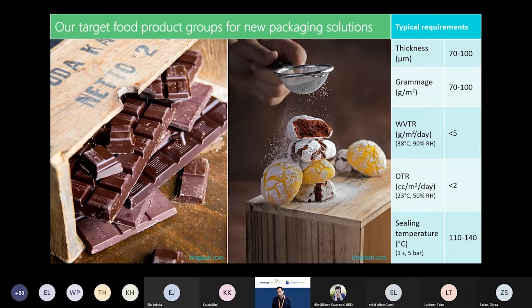So we had chocolate and cookies, and we were looking at the typical requirements for this kind of packaging, especially when it comes to barrier function. And we were looking at potential water vapor transmission rate of less than 5 gram per meter square per day and oxygen transmission rate of less than 2. And of course, these requirements can vary a little bit depending on what product you are packing. So these were the targets that we had kind of set for ourselves with our new packaging materials. We wanted to see how close we can get to these targets.